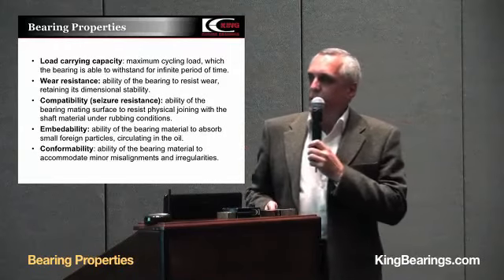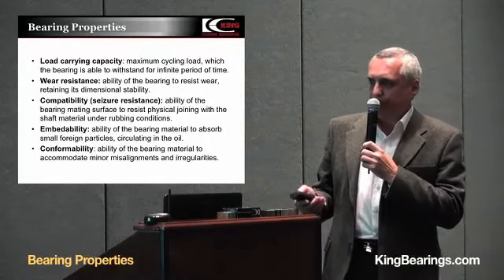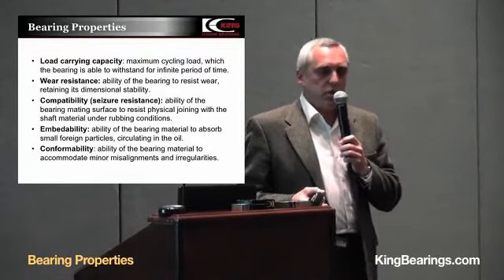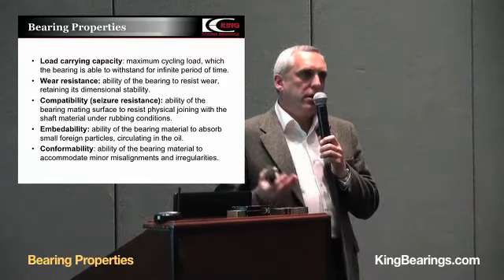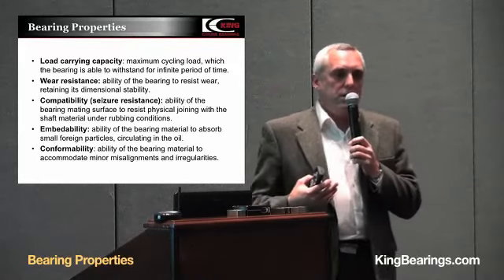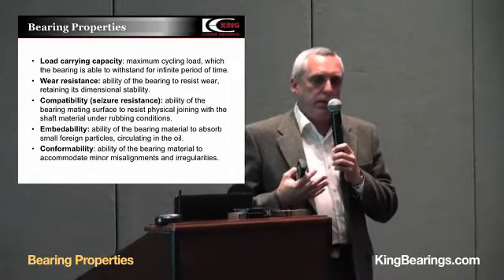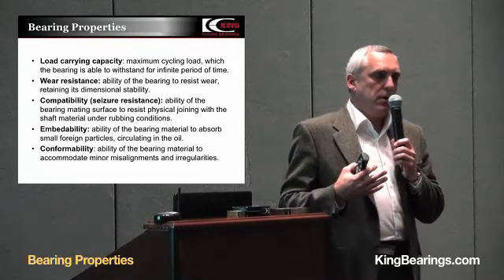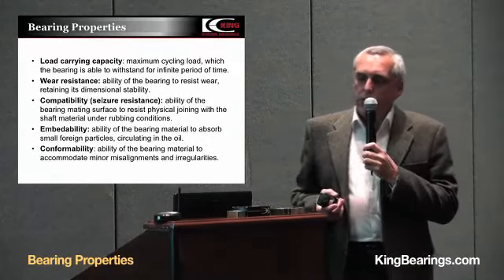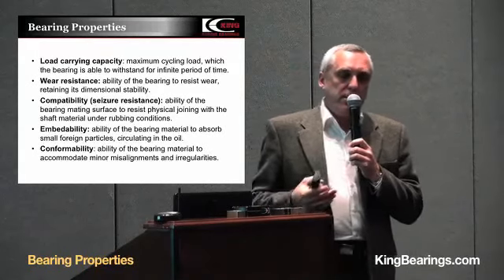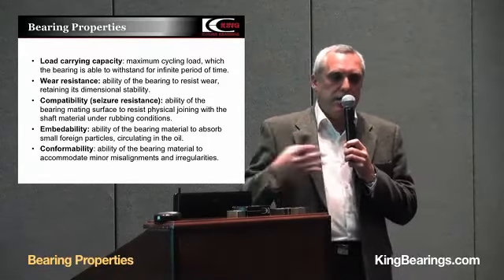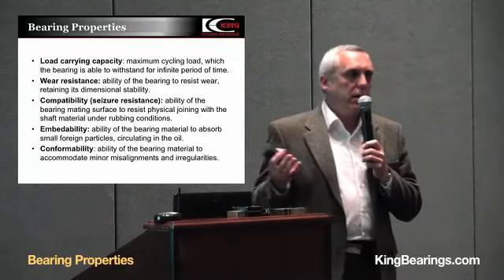This is about materials engineering — it is possible. How is it possible? The bearing has a layered structure. First of all, it has a steel back. Actually, 80% or more of bearing weight is steel. Steel is needed for providing good contact with the bearing housing — press-fit. Steel is support; it is not anti-friction material, it is not bearing material. Over the steel, there are layers of different bearing materials. To provide softness and hardness at the same time, composite materials are used.